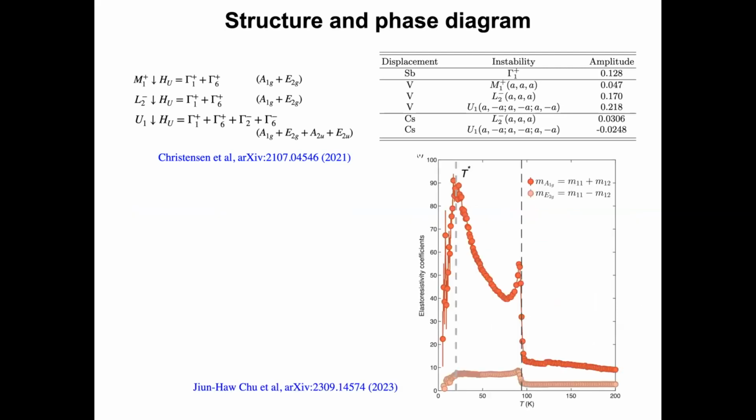This is the data that we saw yesterday, and first of all, it shows that the charge susceptibility is large in the fully symmetric channel. This is A1G, and I will show Raman data saying that point group symmetries are not broken. This also confirms that. There is a weak signal in a non-symmetric channel, and you would expect a weak signal if there is another subdominant order parameter far away. So it contributes to susceptibility, but it's suppressed.